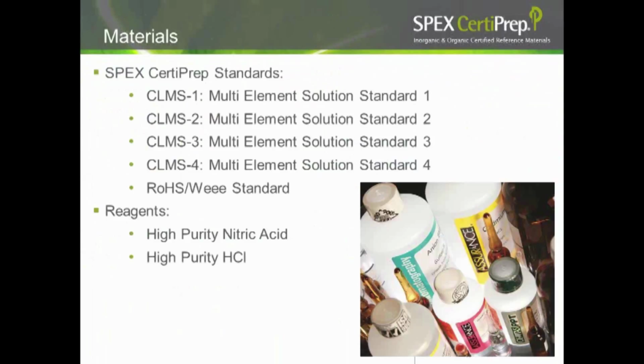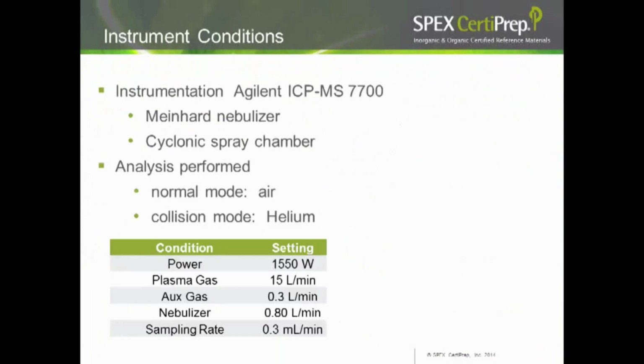For our standards, of course, we used our CLMS suite of standards for ICP-MS and our ROHS standard. We used very high purity nitric acid and high purity HCl to eliminate any potential contaminants. Our study was done using an Agilent ICP-MS 7700 with the cyclonic spray chamber and the Meinhard nebulizer. We did perform a collision mode with helium on our samples to try to avoid some of the polyatomic interferences.